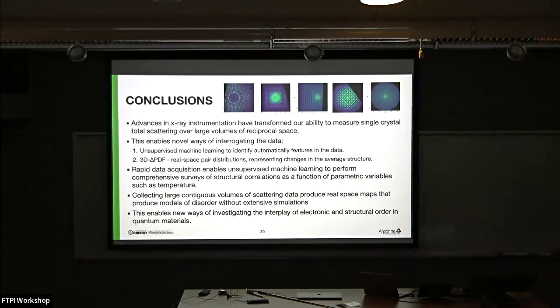But you're right. In principle, if we were to do ultra high resolution measurements on a completely different machine where we did essentially home in on one or two peaks, then it might just be possible. The other thing we've never done, which I regret, is to look in the PDF space, just because I ran out of time to do it. There, you might actually see these decaying tails as changes to the long range correlations in real space. Yeah, and that would actually be a really good thing. But no, you're correct. Please.